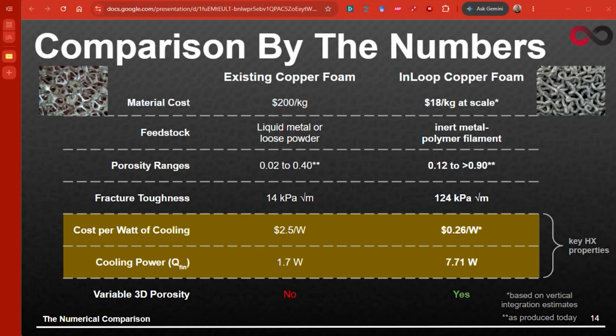Our feedstock is an inert metal-polymer composite filament, compared to existing solutions which rely on molten metal that's casted or loose metal powder, which is a fire hazard. We have a pretty wide porosity range, and we're trying to push those bounds to encompass everything that existing players can do. And fracture toughness is a key metric that we've measured when we mechanically tested these copper metal foams. When we looked at the thermal tests for our copper metal foams, we were really surprised.